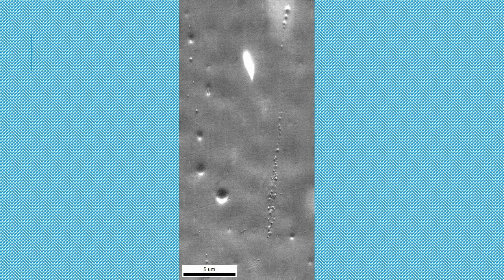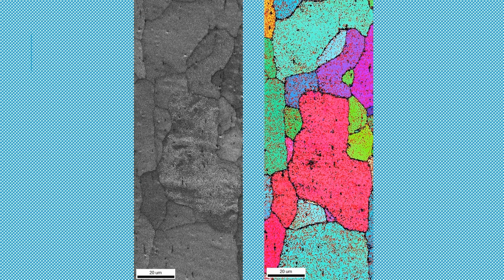To do this, they first do manual polish and then electro polishing. In this slide you can see the SEM image of the accurately polished surface of the aluminum copper oxide composite. As mentioned, the surface must be completely polished, otherwise EBSD analysis does not work or shows vague images. In this slide you can see the image of the aluminum surface which is not well electro polished.